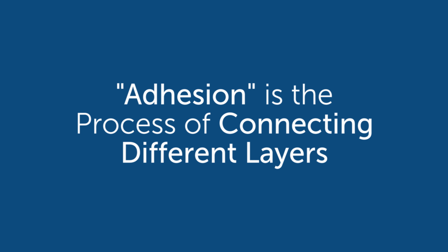And finally, adhesion. There are two types of adhesion. There's the adhesion of the textile to the vinyl itself. There's also the adhesion of the skin layer to the foam layer. First of all, on the adhesion of the skin layer to the foam layer, you have to have a good cross-link between the two chemistries so they become one. In the case of the backing to the vinyl, you want to have at least 4 pounds of adhesion. That is where when you try to pull the backing off, it takes at least 4 pounds per inch to pull that backing off. If not, you're going to have delamination in the field and you're going to have product failure.